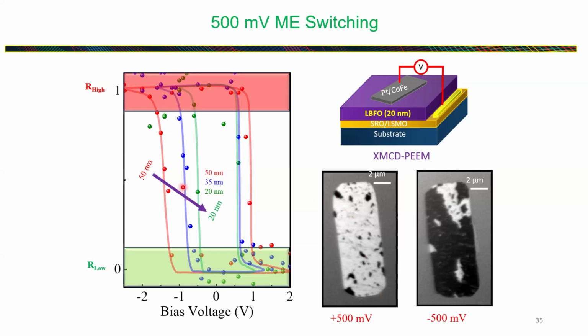And here we have done a systematic study from 50 nanometer all the way down to 20 nanometer. And we have shown that as you decrease the thickness of the LBFO, you can decrease the switching voltage. The switching voltage is more important for engineers, who are more concerned about voltage than the electric field. So if you reduce this voltage below 500 millivolt, that would actually be the game changer.